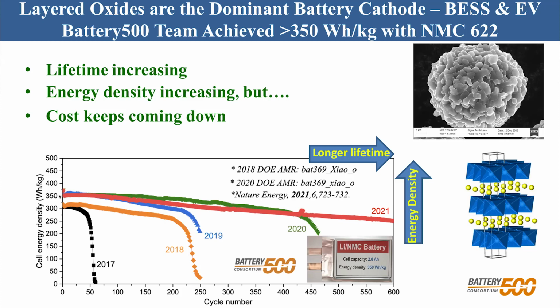It's not extrapolated. So my ex-student Jay Xiao, who's at Pacific Northwest National Lab, they get these cells, they weigh them, they measure the volume of them, and then they do the cycling based on that. And the cycling is then done at Idaho National Lab. So something we try to tell all the startup companies, we won't believe your data until you send your materials to a third party and have it tested, because it's just too much exaggeration at the moment.